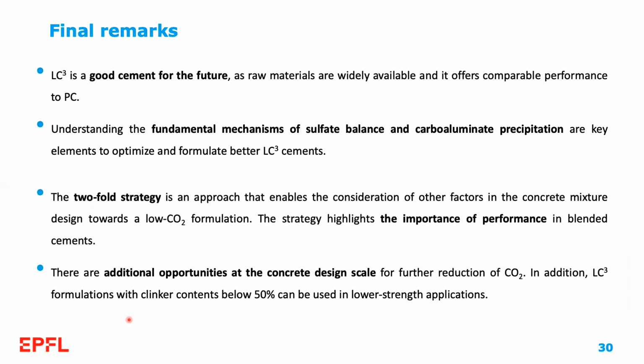So as final remarks, I would like to highlight that LC3 is a good cement for the future. First, because the raw materials are widely available, and also, very importantly, because it offers comparable performance to PC. Understanding the fundamental mechanisms of sulfate balance and carboaluminate precipitation are key elements to optimize and formulate better LC3 cements. The twofold strategy that I mentioned in the last part of my presentation enables the consideration of other factors in the concrete mixture design towards low CO2 formulations.